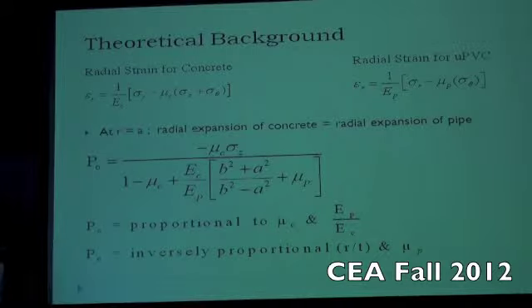At r equals a, the radial expansion of the concrete is equal to the radial expansion of the pipe, because at r equals a both the pipe and the concrete are in contact. If we integrate both of these strains by their respective volumes and equate them to each other, due to the boundary condition that the edge of the concrete is touching the pipe, so both the expansion of the concrete and the pipe have to be equal, then we get this. We end up with this expression for the confining pressure for pipes.